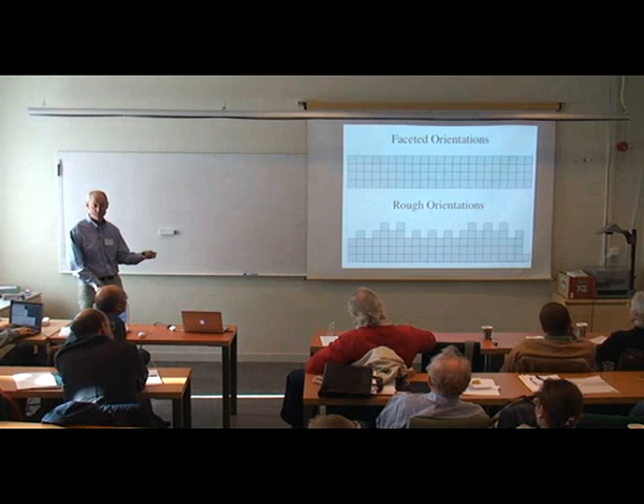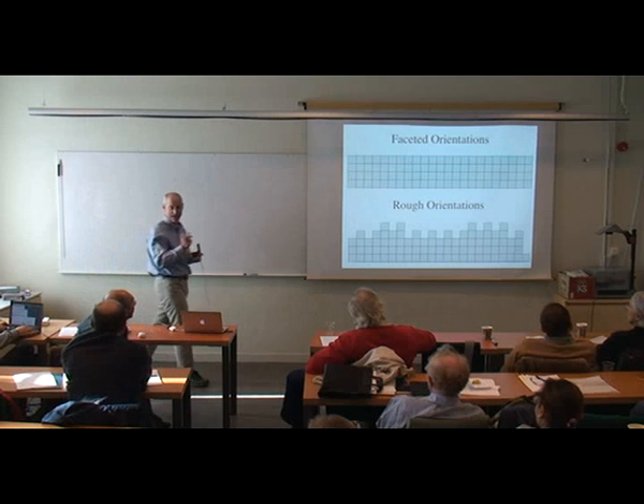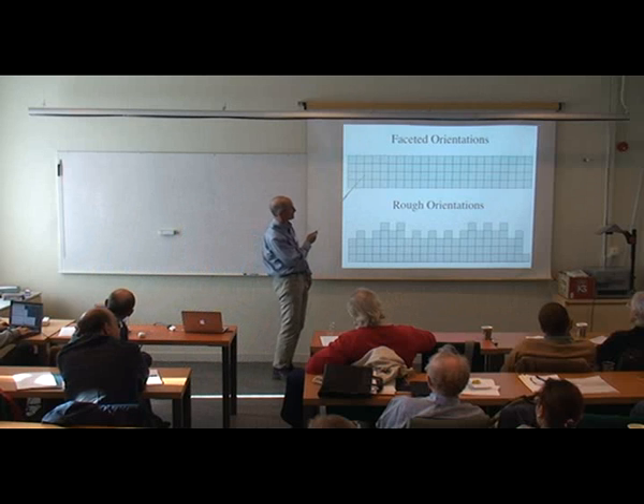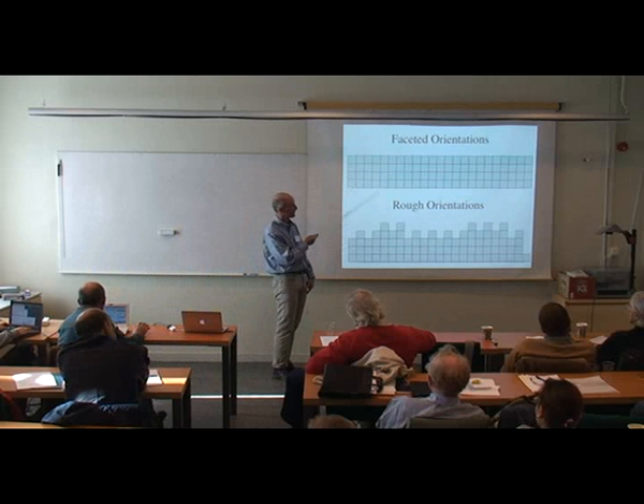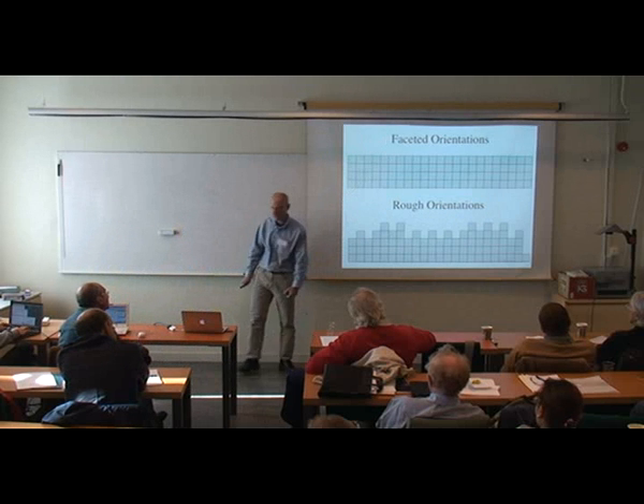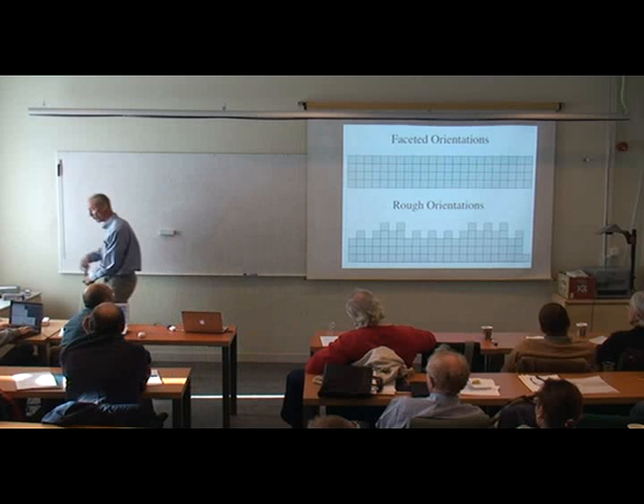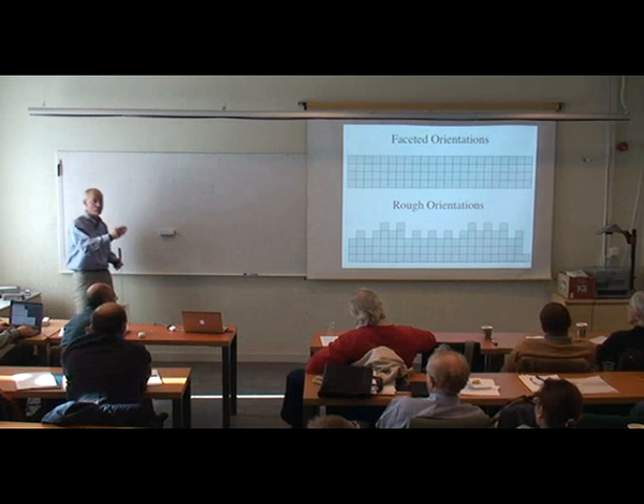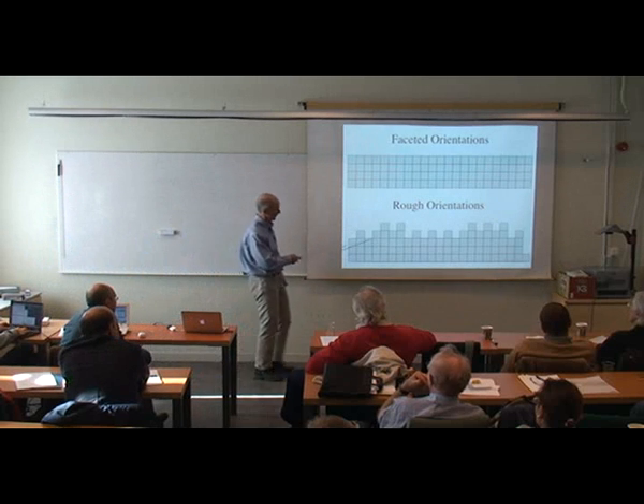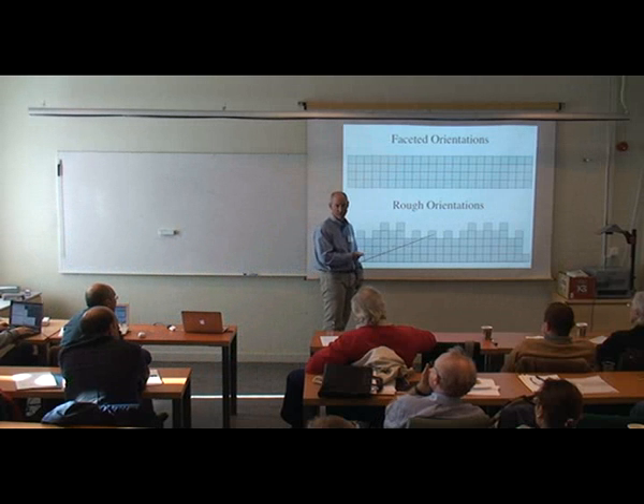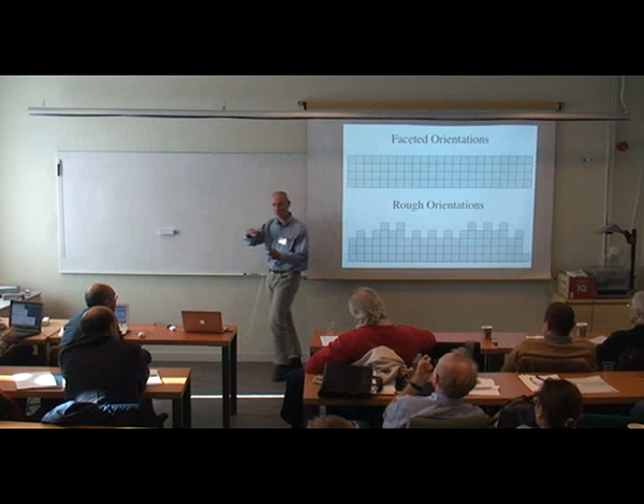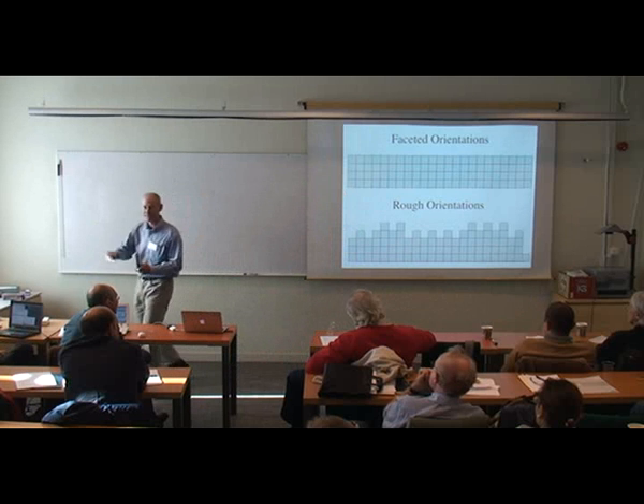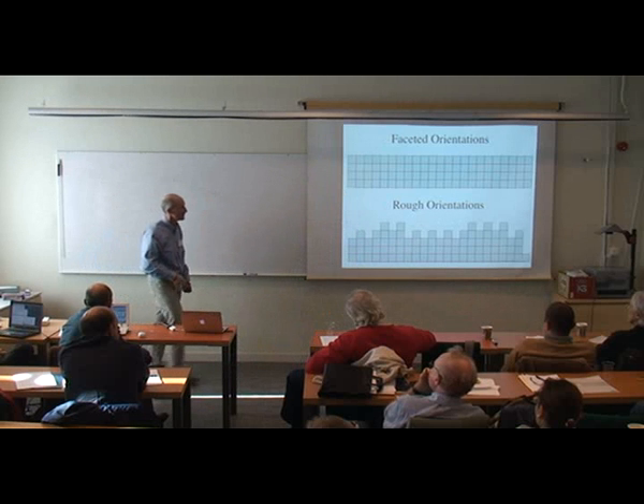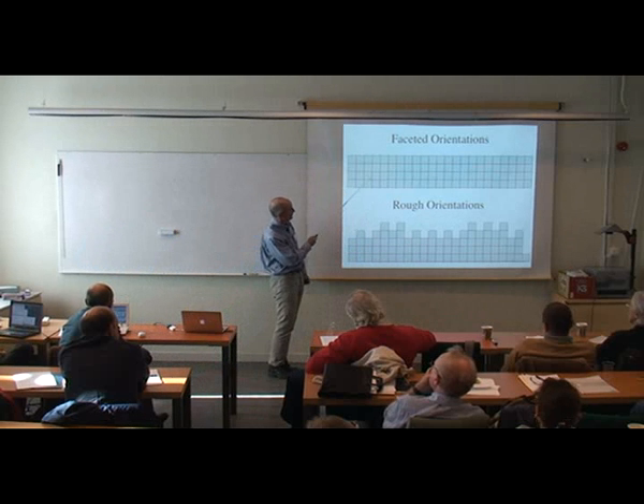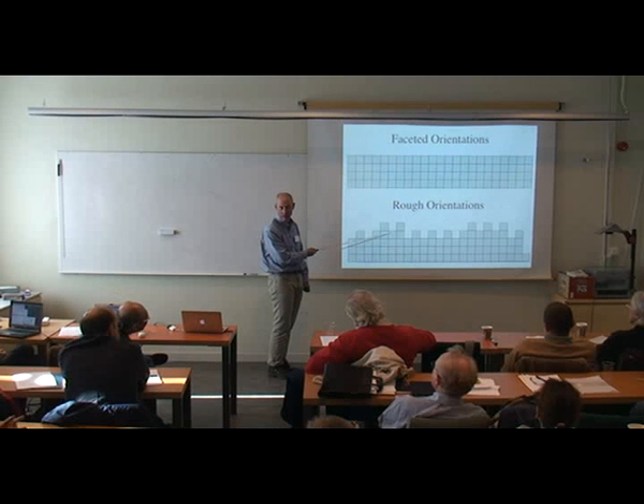Okay, there are two types of orientations that coexist on a surface, or can coexist on a surface. One is molecularly smooth, one is molecularly rough. So you can just think about it exactly like this picture. If you walk along the surface taking steps slightly larger than a lattice parameter, then you have a molecularly smooth surface. And here's a hill and valley structure on the scale of a lattice parameter. Okay, so on a single crystal, like you saw in these Wulff shapes, I can have these things coexisting. Smooth and rough orientation. Moreover, I can take one of these and make them into one of these, and that's a critical phenomenon. Okay? That's the roughening transition.